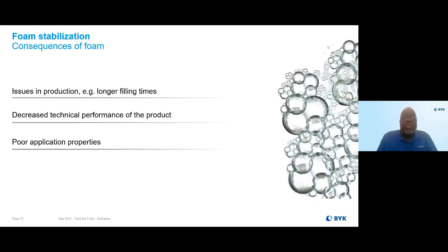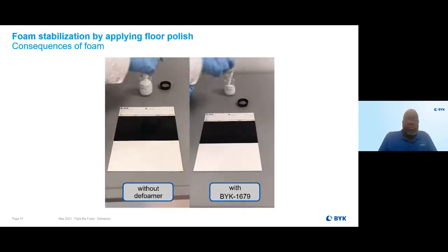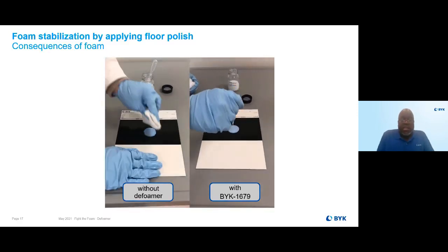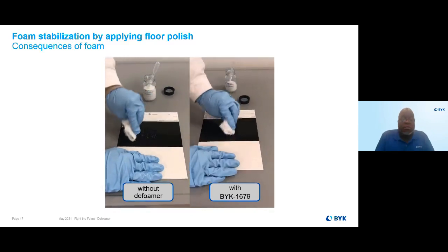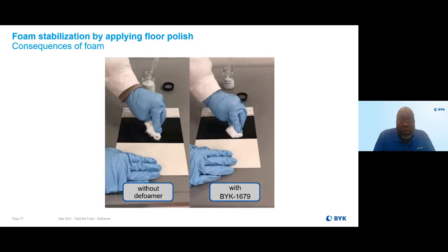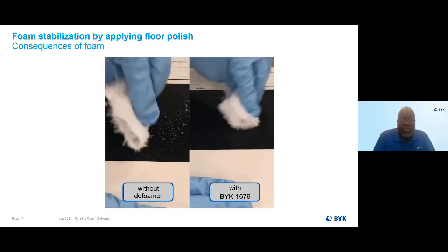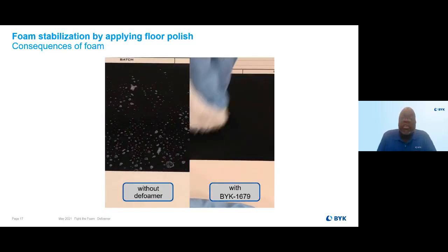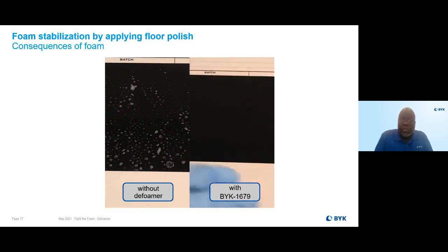I have spent a great deal of time finding a proper defoamer in a floor finish system. And the interesting thing is, it gives rise to why there are so many defoamers. I have experience where BYK-1679 works great in this application, or even better in this formulation. I have seen very similar formulations where it's still a floor finish, but instead of BYK-1679, I may have to go with 094 or one of the other products, simply because of a change in the polymer in that formulation.